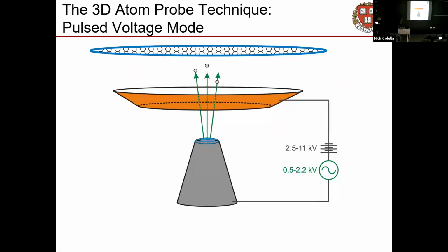Why? Well, the way this thing works, remember, we're doing time-of-flight mass spectroscopy. You've got to blow your sample apart. We got to rip atoms right out of it. And we do that with really big electric fields. We want to get fields on the order of several volts per angstrom, which is an absurd electric field. That is stronger than the fields that are actually present between 2 bonded atoms, which is, of course, the point. The whole point here is we want to overwhelm the bonds keeping your material in one piece and rip it apart. You cannot produce fields like that on a bulk object.